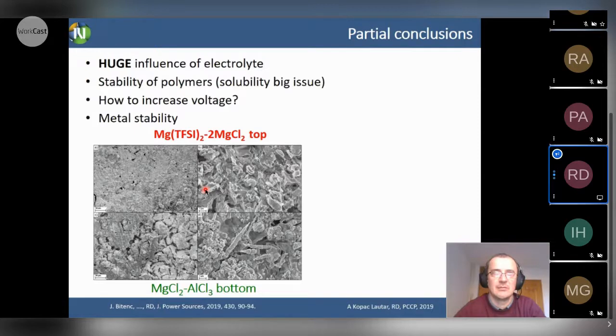magnesium is also a metal which can be deposited back in a non-uniform form, and again it depends a lot on the electrolyte type. You can have a flake type of deposition which still can grow through the separator, or you can have even some kind of needle type of deposition. For example, again, in this MgCl2-AlCl3 type of electrolyte, which is then much more dangerous because this one can grow much faster through the separator and make a short circuit.